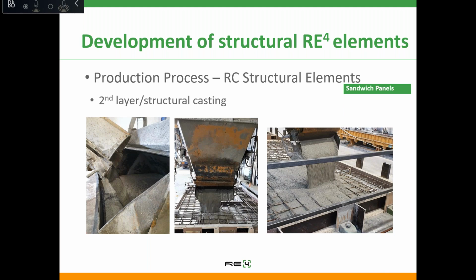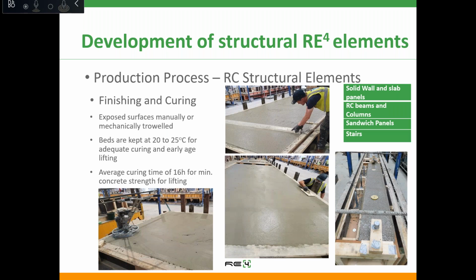Then the second layer of the sandwich panels is cast in a similar way as I explained before. We get the concrete from the batching plant and using the skip, the structural layer is poured. After all the casting of the concrete elements, and as soon as the concrete begins to harden and the consistency of the surface is adequate, these elements are manually or mechanically trowelled depending on the level of finish required.